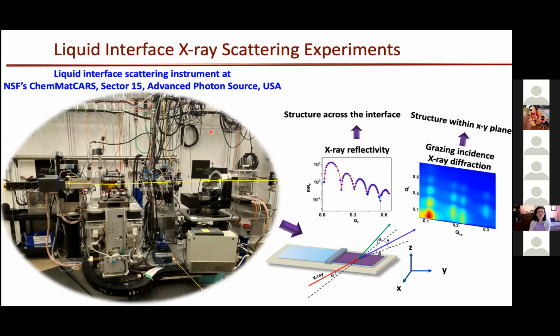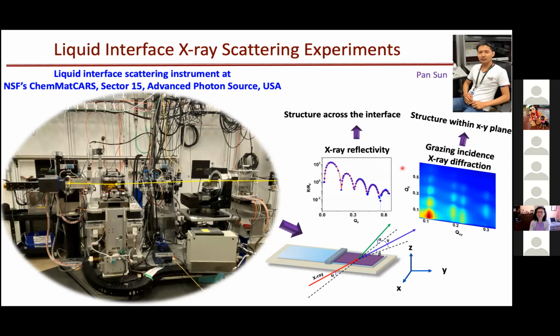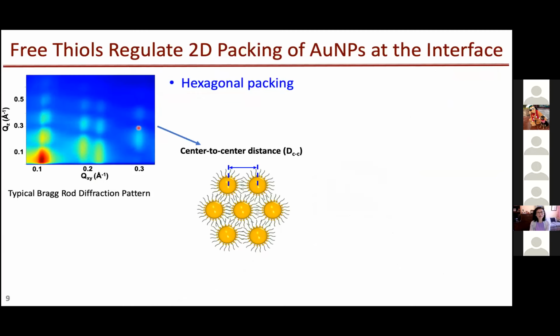Using this instrument, we measured the X-ray reflectivity and the grazing incident X-ray diffraction. Pan Sun, our postdoc, did most of the experimental work and data analysis. Here we show the typical Bragg rod diffraction pattern.